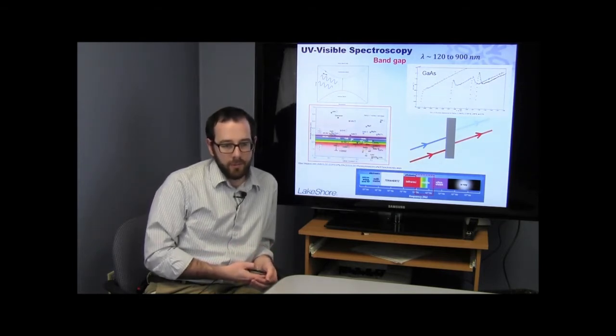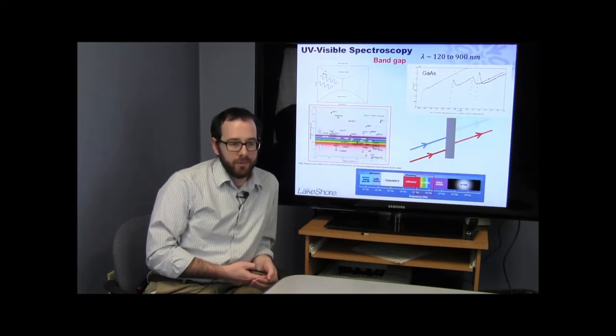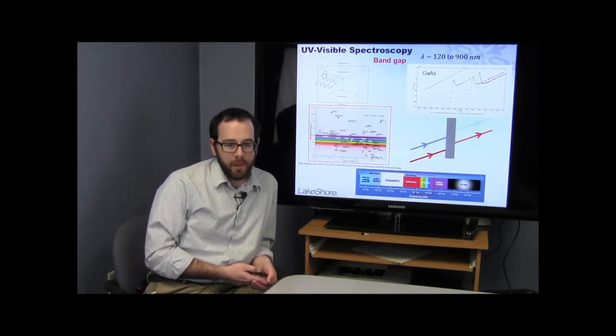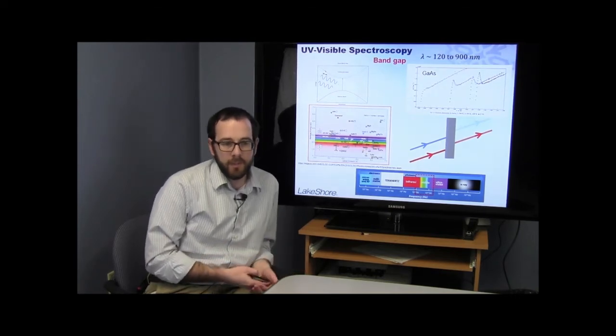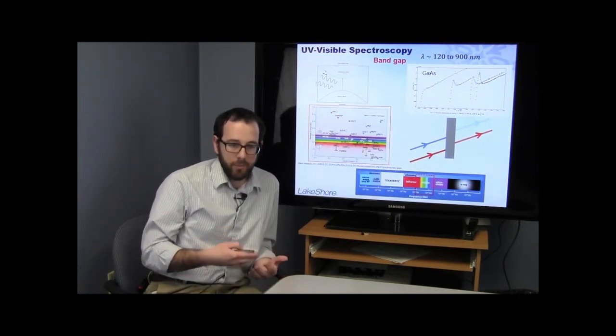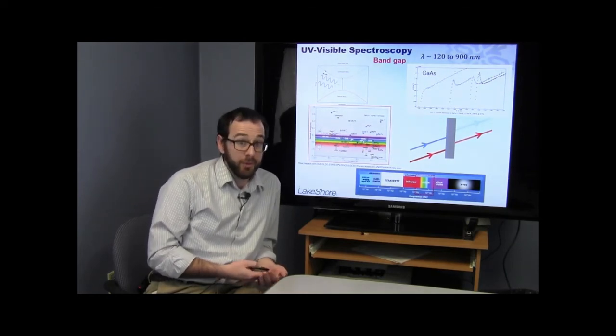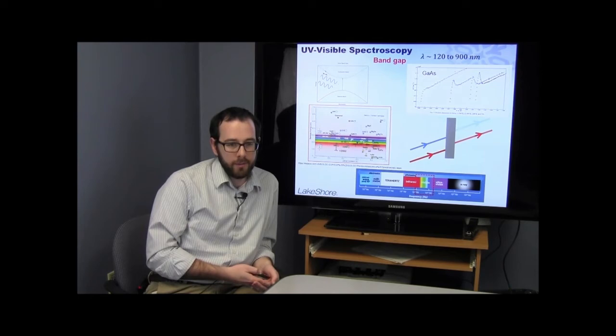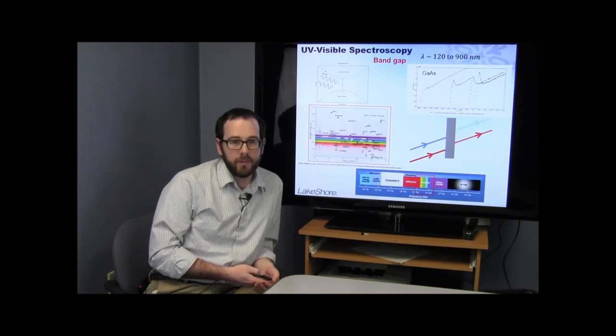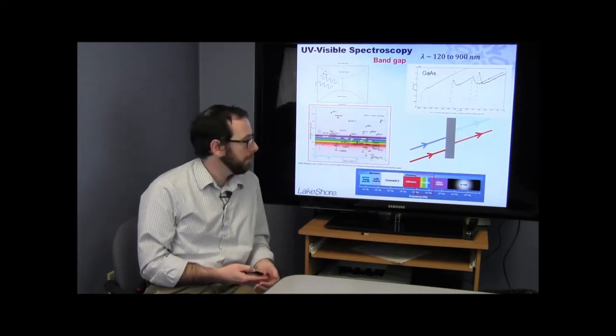And so certain semiconductor materials which have very small band gaps, for example the indium arsenides and the indium antimonides, are going to absorb radiation all the way from the far red through the UV region, whereas wider band gap semiconductors, for example diamond, actually have very broad band gaps, and so they're going to absorb only the highest energy, or the UV region of light.